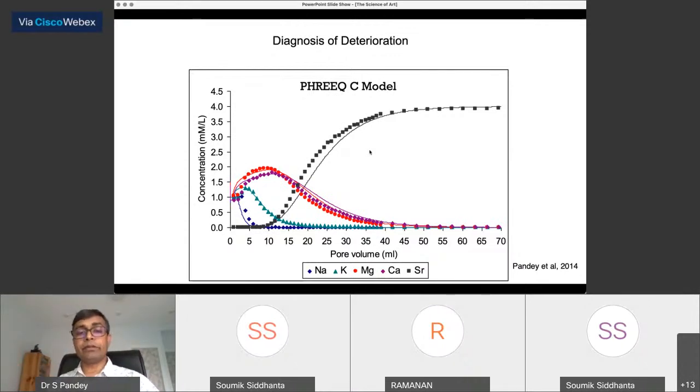If this happens, these salts like sodium chloride and potassium chloride exist in only one phase. The damage caused by these salts is much lower as compared to salts that can stay in multiple phases, like sodium sulfate, for example, in two different phases, thenardite and mirabilite. One is anhydrous sodium sulfate, the other one is with 10 water of crystallization.